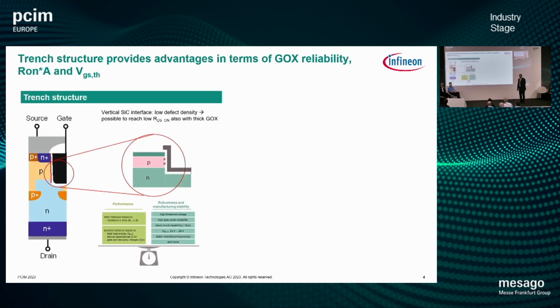The most important question is always: why the trench structure? From the trench structure, we clearly see the advantage of the aligned channel plane, where we have very good channel mobility and also a very low defect density. This combination of a lower RDS(on) times A, a higher threshold voltage, and, most importantly, much more robustness in manufacturing allows us a very good balance in designing